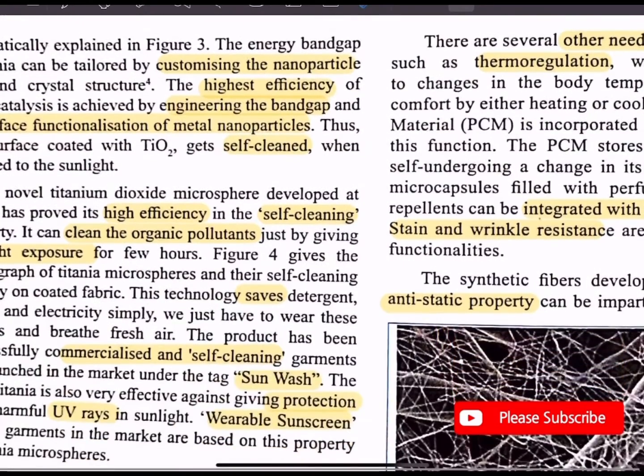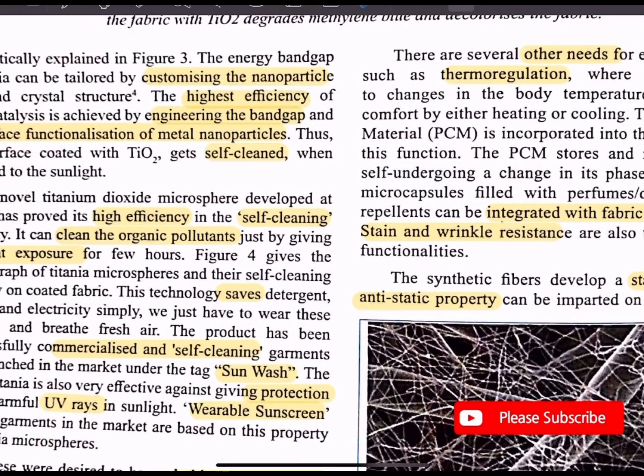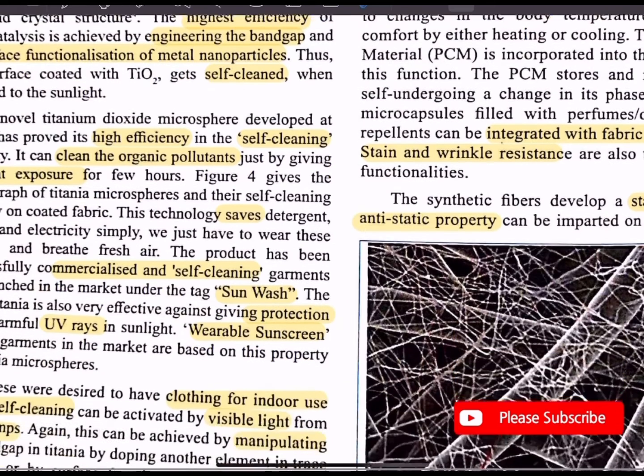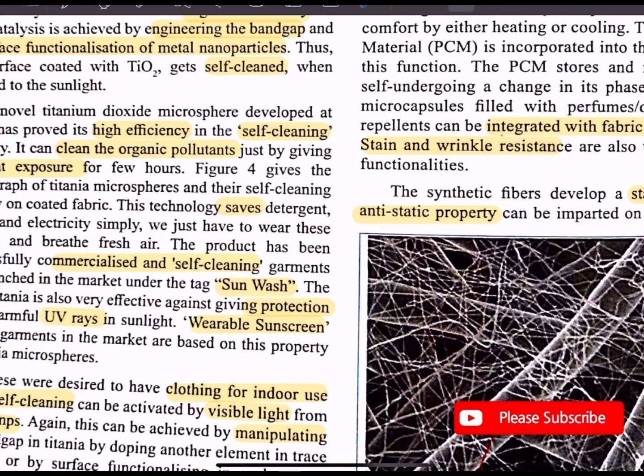Thus, a surface coated with titanium dioxide gets self-cleaned when exposed to sunlight. A novel titanium dioxide microsphere developed at ARCI has proved its high efficiency in the self-cleaning property. It can clean the organic pollutant just by sunlight exposure for a few hours. The micrograph of titanium microspheres and their self-cleaning activity on coated fabric is schematically explained.